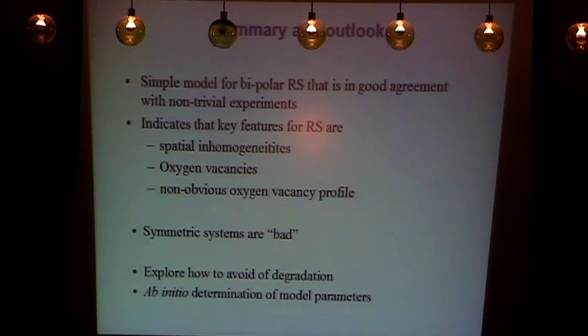It's much better to have an asymmetric system. So already this model is providing good guidance for system design. Also, we can explore and have started to explore the effect of degradation. If you remember the results that I showed, all these tables with legs as a function of loops, you see that there was some drifting of the system. The drifting is nothing but the degradation of the system, and it's that the vacancies get trapped into the bulk, and then it's harder to get them out of the bulk again to the interfaces. So those are features that you can also start to understand.